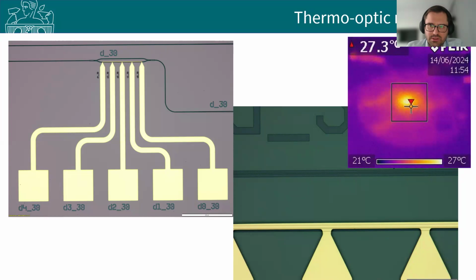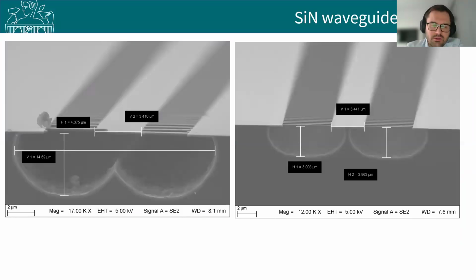And thermal modulators. And here are some waveguides which are suspended. So they are for mid-infrared, which is quite interesting for gas sensing, because each gas has its own fingerprint in mid-infrared, but in that spectrum, the silicon oxide is making attenuation for the light, so we cannot have a waveguide lying on the silicon oxide. So one of the methods is etching the oxide or silicon from below the waveguide.